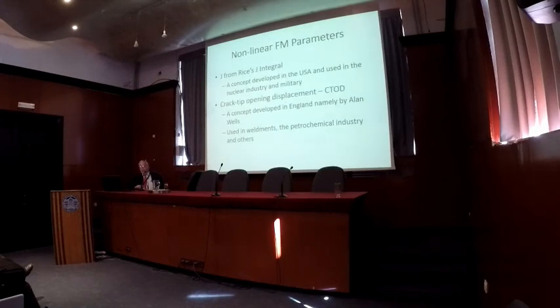So here are some of the parameters that people use. The J is from Rice's J integral, and that was developed in the U.S. and used in nuclear industry and military in the U.S., somewhat in Europe. Crack tip opening displacement was developed in England, mostly by Alan Wells. It's used a lot in weldments and in the petrochemical industry in the U.S.